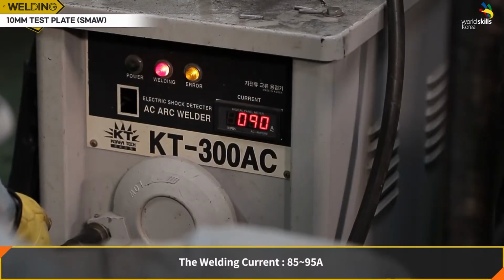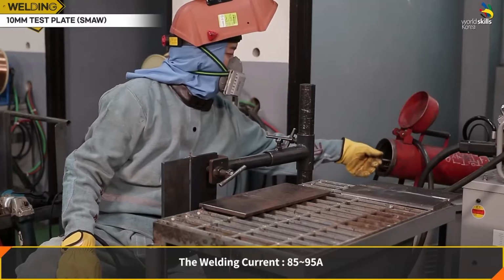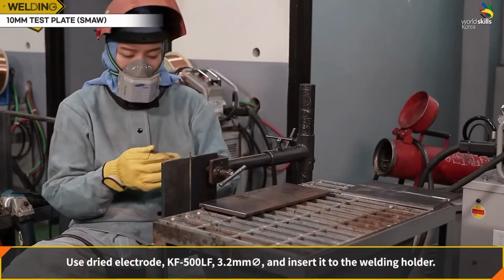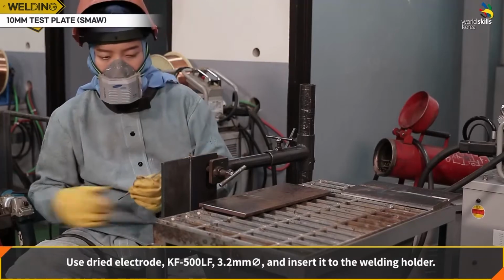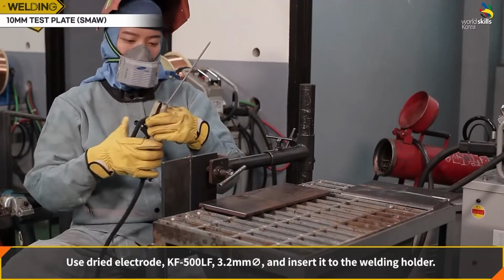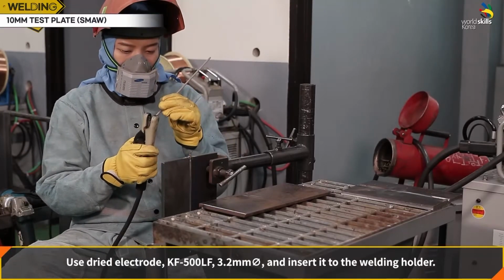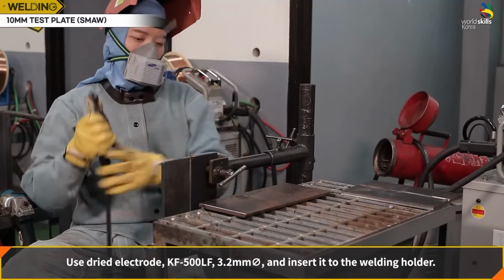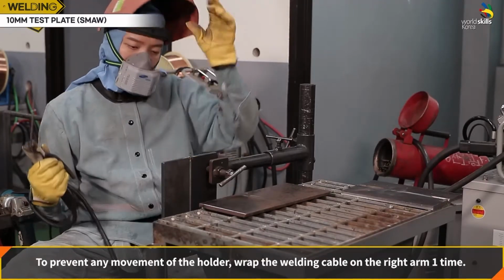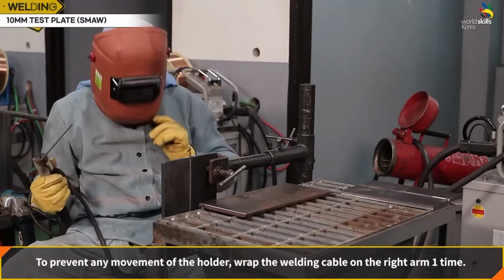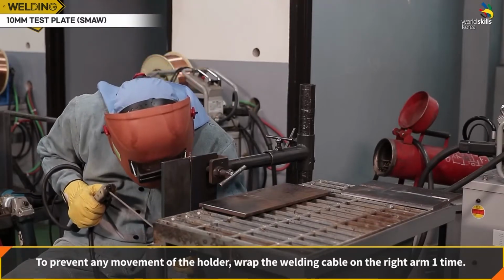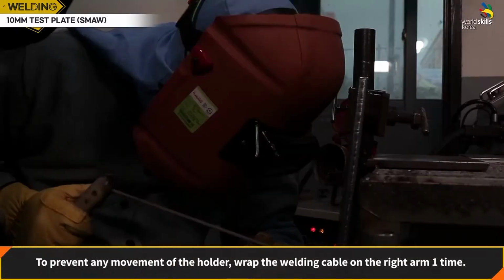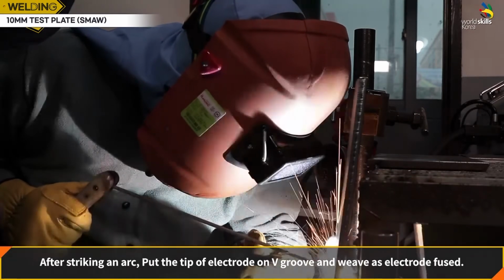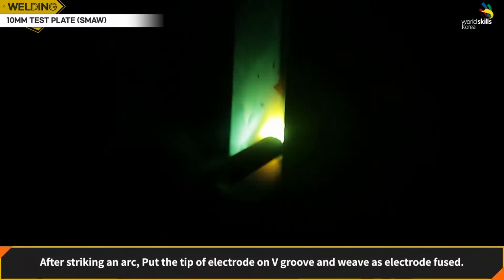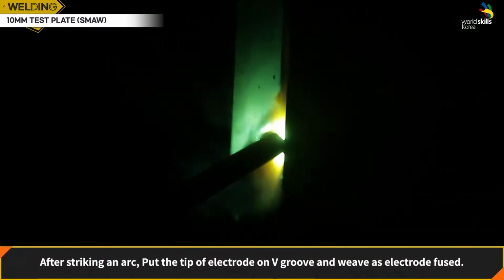The welding current, 85 to 95 amps. Use dried electrode, KF500LF 3.2 mm, and insert it into the welding holder. To prevent any movement of the holder, wrap the welding cable on the right arm one time. After striking an arc, put the tip of the electrode on the V-groove and weave as the electrode fuses.